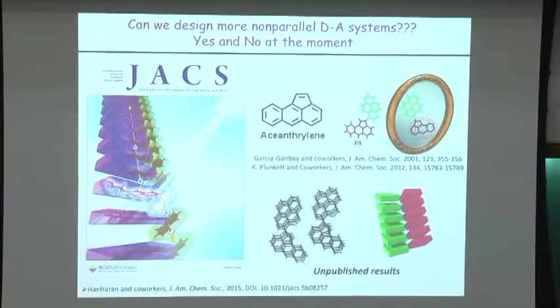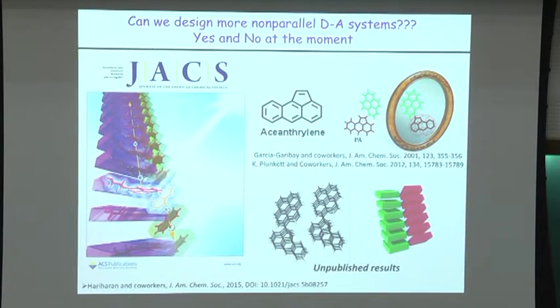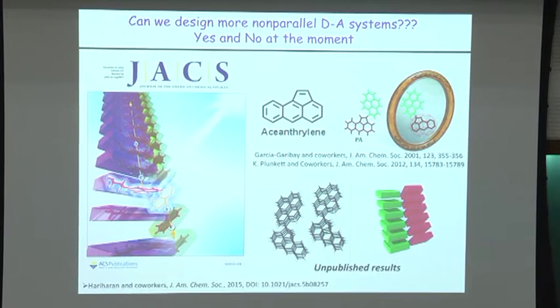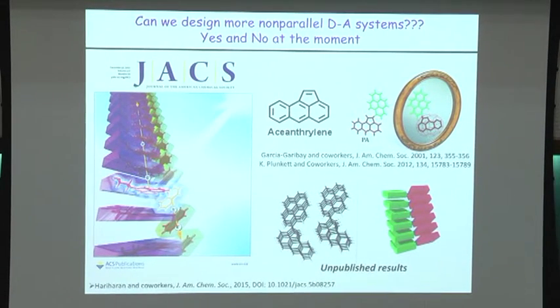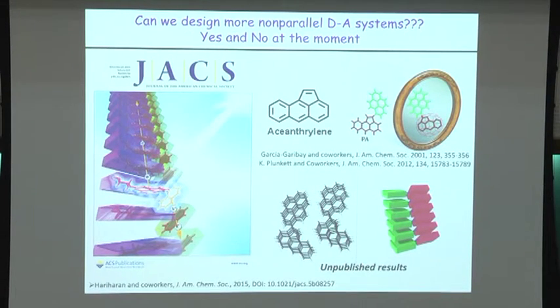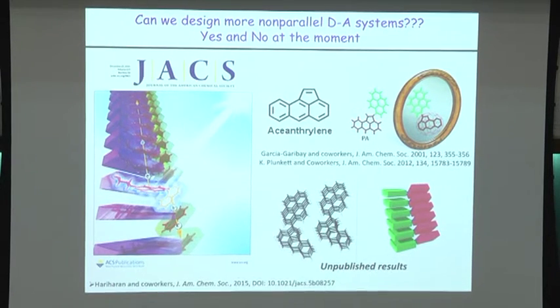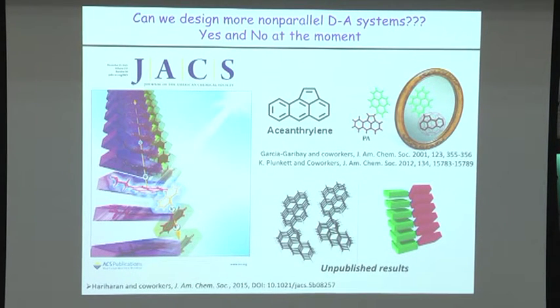We are measuring the conductivity of this material in the single crystal, and we see that the mobilities are comparable not to rubrene, but to pentacene, which is quite good, but not as good as rubrene. So, the conductivity and mobility both are comparable to pentacene, but not to rubrene. And the dimension of the single crystal? This one we can grow in almost half a millimeter size.